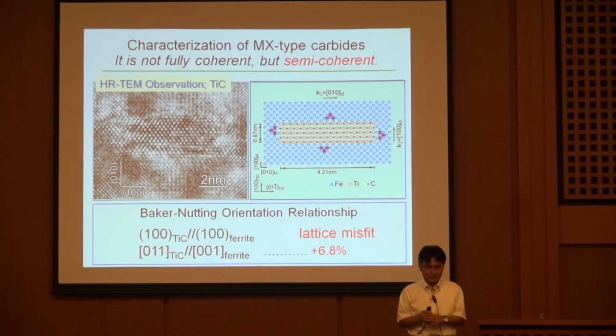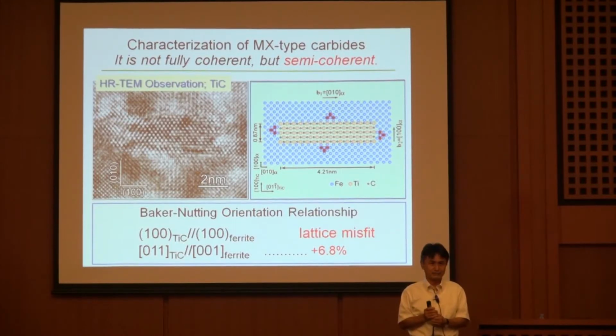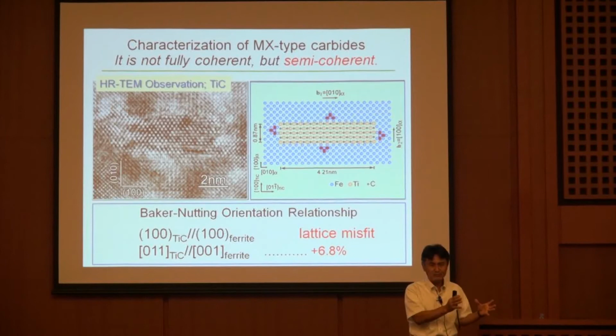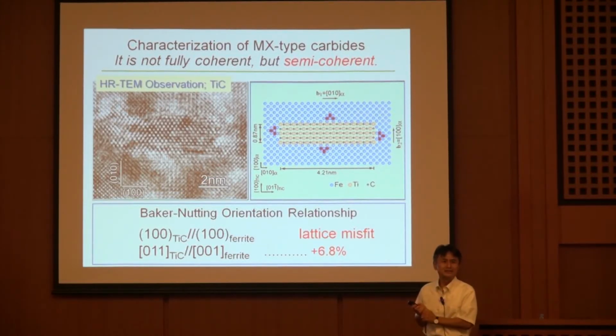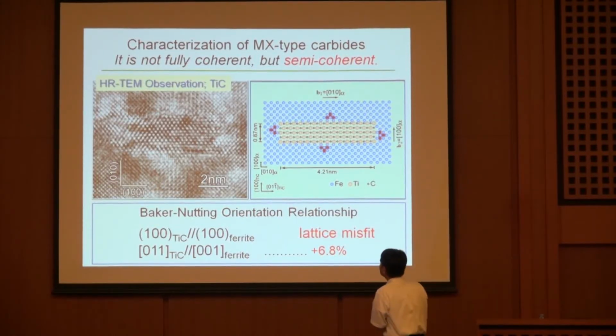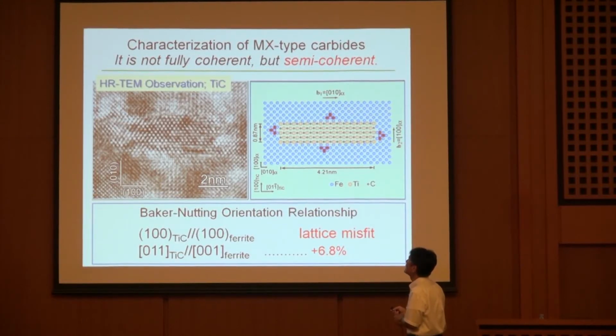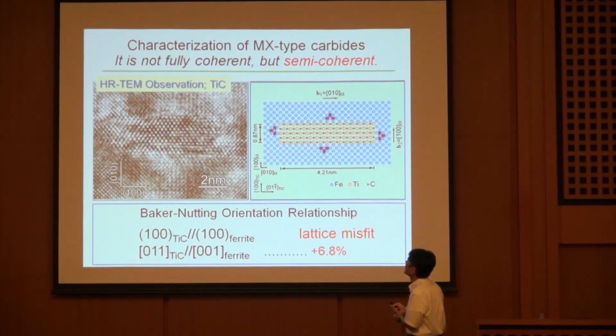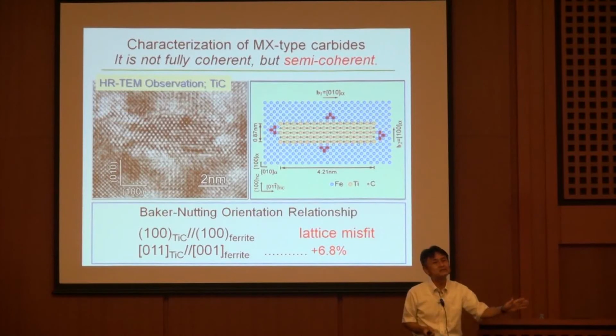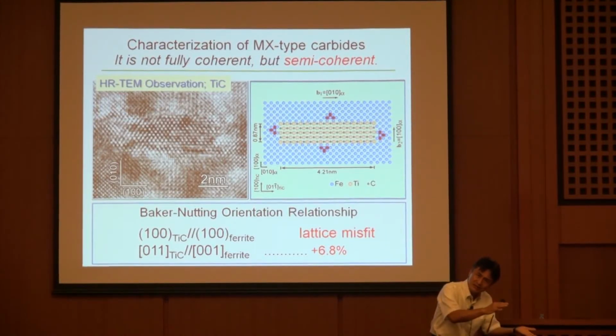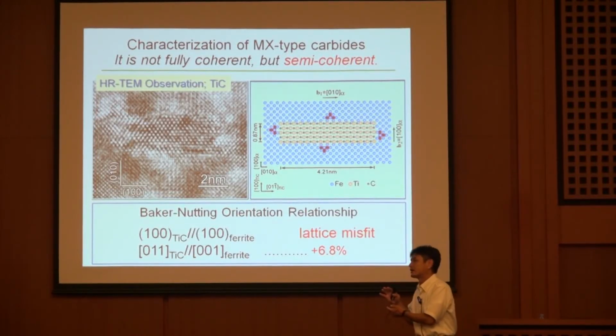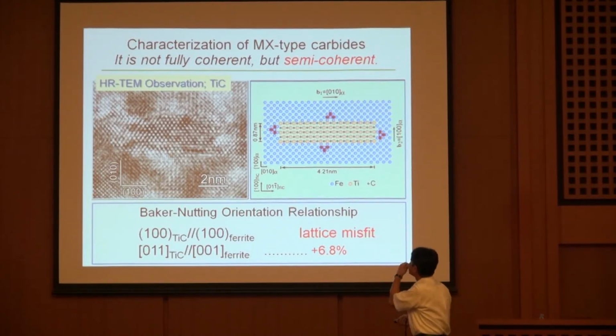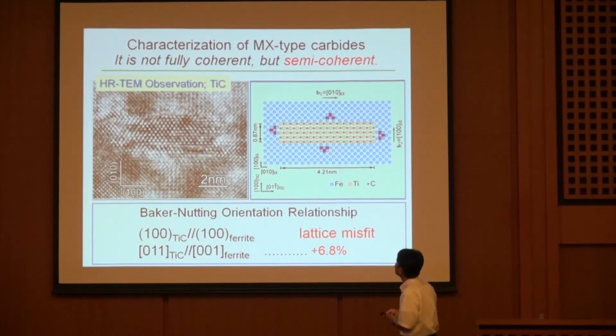We did many things to find out this reason, and the result I show you today is a part of that. I believe this is the essence of the reason. What we considered is the character of MX type carbide in the atomic scale. It's the interface morphology of carbides: coherent interface, semi-coherent interface, random interface, something like that. In our case, the interface isn't fully coherent, but semi-coherent.